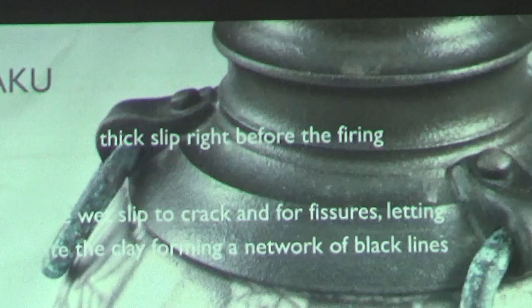I finish dousing this thing in this thick putty-like slip, and then I immediately will put it into a kiln that's already 1,200 degrees. And so it starts cracking and crazing because it can't handle the heat change. The heat causes the wet slip to crack and form fissures, letting the smoke inundate the clay and forming a network of black lines across the surface.